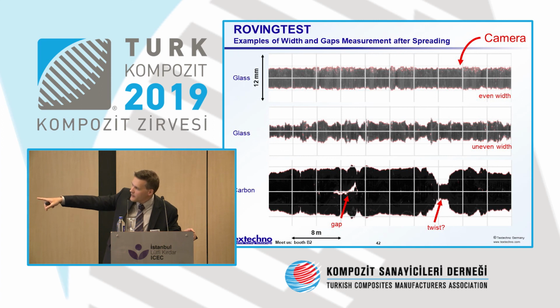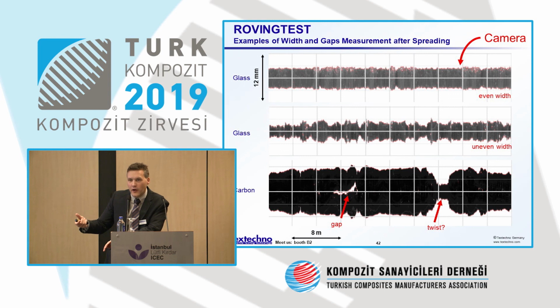And finally, the carbon example is also interesting. The width is way wider than on glass in this case. And in between, you see there's a gap forming, where after spreading the yarn actually splits in 2, and then after a while it comes back. You also see that there's a thin place where the yarn is not as wide, and that was actually a false twist that was on the bobbin and is now coming through the machine. And false twist, of course, hinders the yarn from going through the spreading process properly. So these are the kinds of properties that you're able to measure with the roving test.